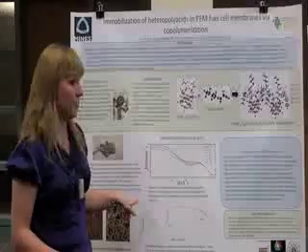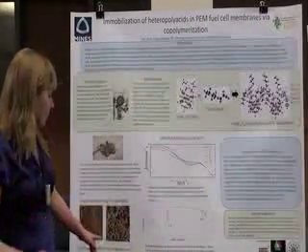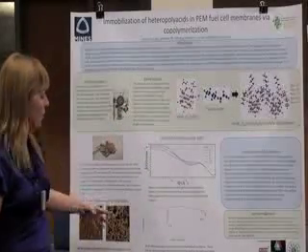Okay, and so for the butyl acrylate membrane, the results I've gotten are shown right here and here. This is an AFM image that I've taken using atomic force microscopy, and it shows the channeling that's created through the butyl acrylate, which is really important because that's where proton conduction occurs.